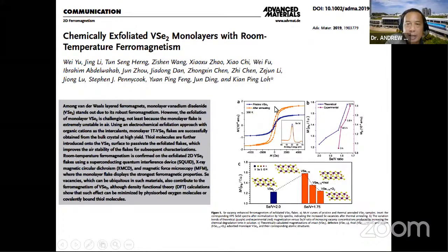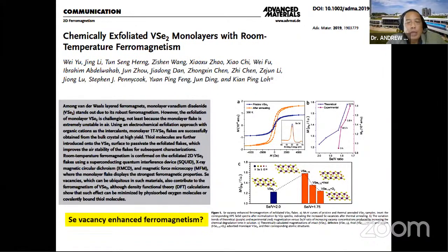And the fact that they observed some magnetism in the intrinsic vanadium diselenide could be due to the fact that they did the whole experiment by chemical means. It means that the samples were exposed to chemicals, exposed to air, and inevitably some external adsorbates or impurities may cause this magnetic signal. So, we postulated that selenium vacancies could cause the ferromagnetism observed.